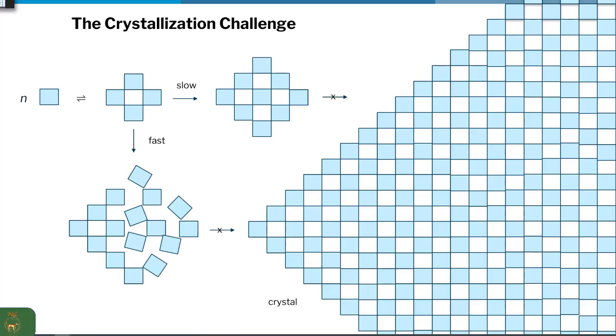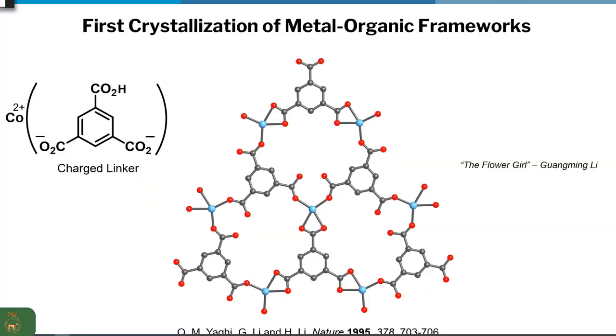And in plain words, we were successful in identifying the conditions, the recipe, to balance the thermodynamics and kinetics and make crystals of what otherwise would have given you a very broad X-ray diffraction. And this was it. This was the very first compound we made from a trimesic acid that is negatively charged with cobalt 2+. And this is the first example of a crystallized metal organic framework.